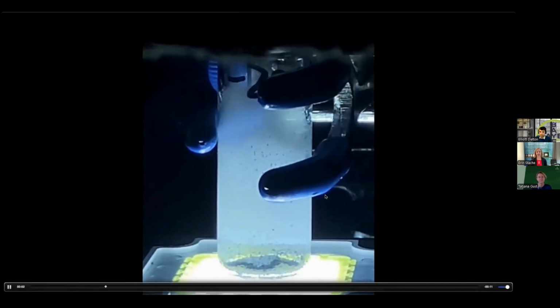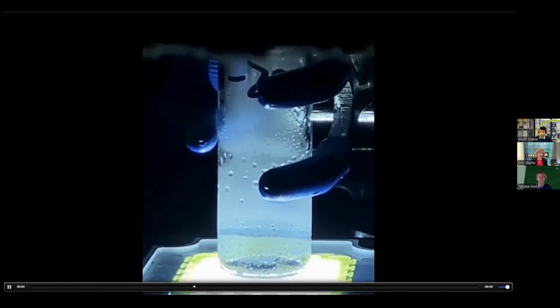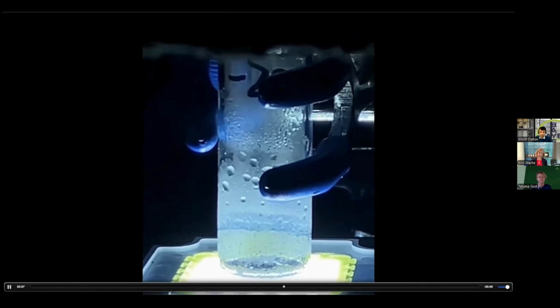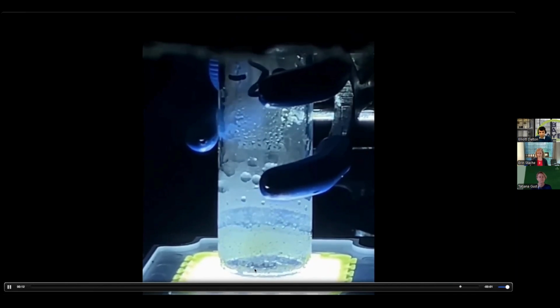But a video is worth a lot more than anything I could say. And so this is a sped up video of our depolymerization process. So you can see as soon as we turn on the light, it starts generating those thermal gradients, starts homolyzing those carbon-carbon bonds and depropagating to styrene monomer. So you saw some bubbling down here. That's the styrene monomer escaping the system. And you can see it's collecting up on the vial and being pulled into the vacuum distillation. And what's left over is some of the trimer, as well as leftover styrene oligomers and carbon black. But it's incredibly fast. I mean, this video is very fast, but it takes about 20 or 30 minutes to